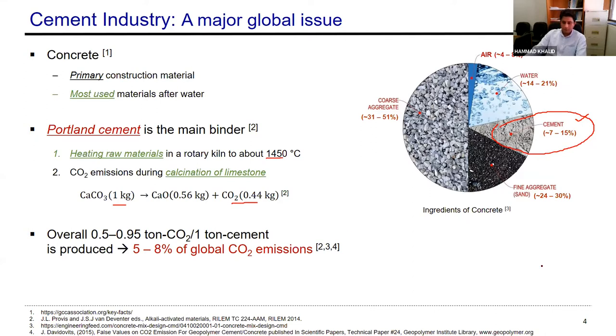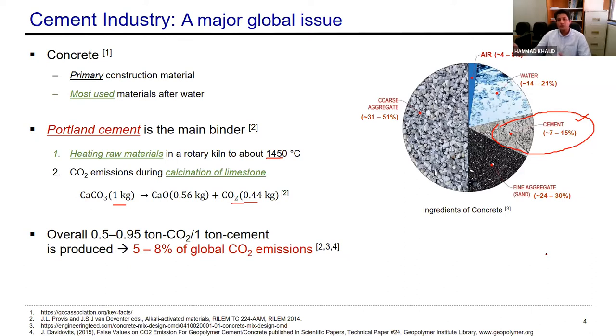There are two things contributing: one is the high temperature, and the other is basically coming from the calcination chemistry of the raw material. In terms of high temperature, we have done pretty well by increasing efficiency of cement manufacturing plants — introducing preheaters, flash furnaces, and circular utilization of emissions from the main kiln. We have done quite well in reducing overall impact. In the future, with greener fuels and greener options for electricity generation, this can be reduced further. But at the same time, we have to look for other raw materials and other sources.